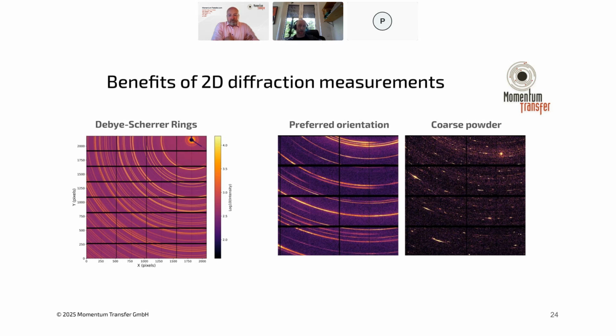For an ideal powder, meaning that you sample all of the crystallites in all orientations, then this should be azimuthally homogeneous or symmetric. And then having the 2D image doesn't add any information, so we integrate it all down into a 1D pattern. However, if you have a non-ideal sample, for instance, if you have preferred orientation where the crystallites are aligning in a certain direction, you can see streaks in your rings. Or if you have a coarse powder, meaning that you have very large crystallites and you're only sampling a minimal distribution of particle orientations, you start to get spots in your data. This is more difficult to detect when you don't have these images.